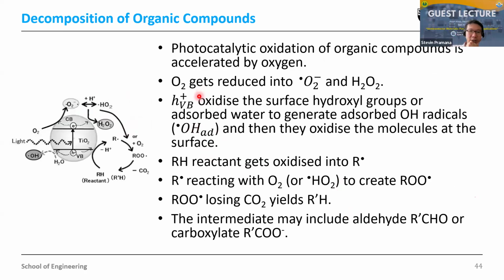So specifically for titanium dioxide, for the decomposition of organic compounds, there are various mechanisms, and this is one of the accepted ones. You get photocatalytic oxidation of organic compounds, commonly accelerated in the presence of oxygen. When the light creates a charge separation, the electrons will reduce the oxygen into an O2 minus radical. And when it reacts with H plus, you can make either hydrogen peroxide, or simply the HO2 radical, with the lone pair electrons.